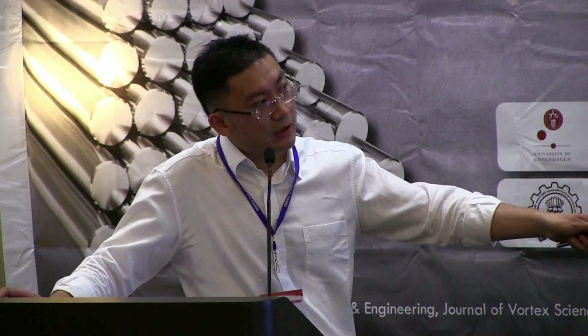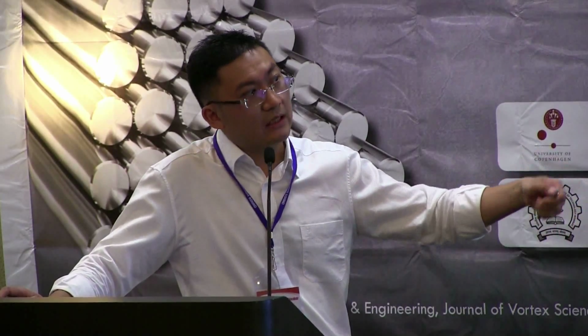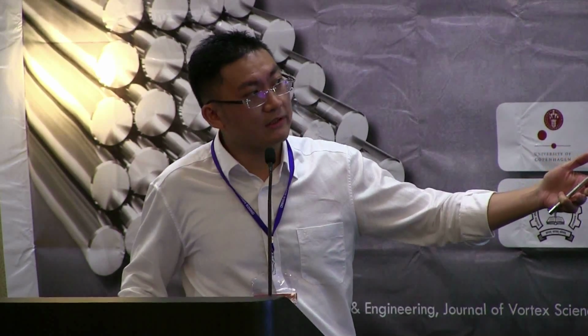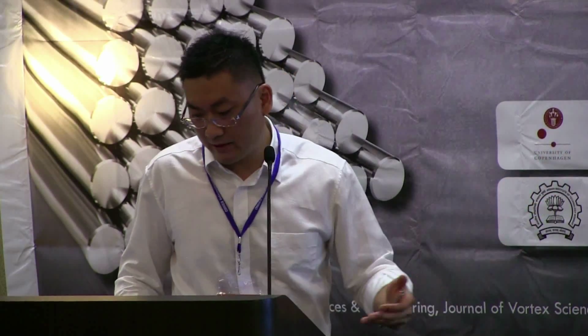We also carried out, actually we have other data but didn't present it here. We compared platinum and palladium alone. They are much lower here. So the alloy is much better.